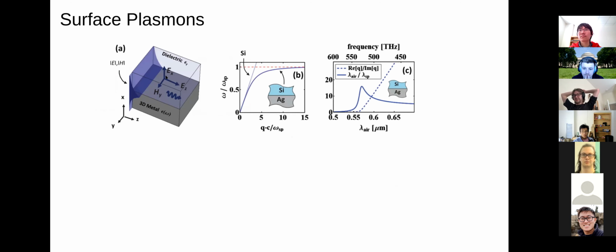And because of the negative value of the permittivity, if you solve for the dispersion, you'll find that there are these basically waves that are confined to the surface, and moreover, their dispersion relation is different than the dispersion relation of the bulk silicon substrate, which means that they're further along in the wave vector direction, so they have wavelengths that are shorter than the wave would be in free space. And this is something we refer to as confinement.